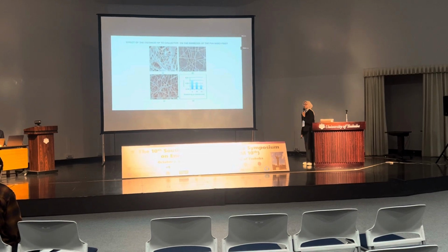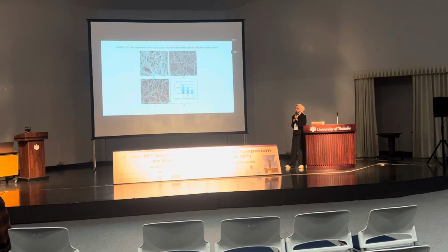Here is the effect of the distance of the tip to collector on the diameter. It was observed that when the distance of the tip increased from 5 to 10 to 15 centimeter, the diameter of the nanofiber was reduced.